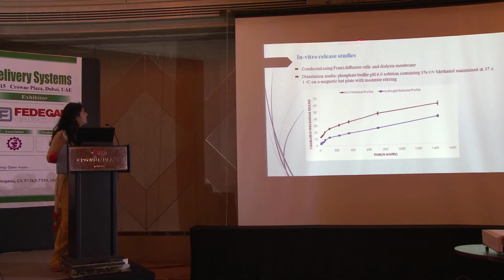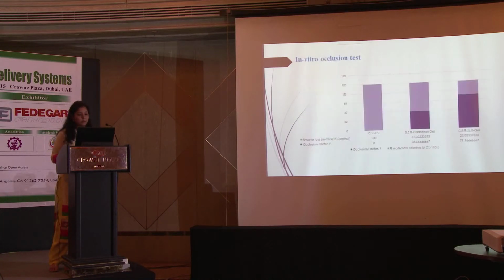In the in vitro release studies, again for the hydrogels, this hydrogel is the in situ hydrogel. We find that there is sustained release up to around 24 hours, and the release is further decreased. SLNs do decrease the release, but the hydrogels further reduce the release of the drug.